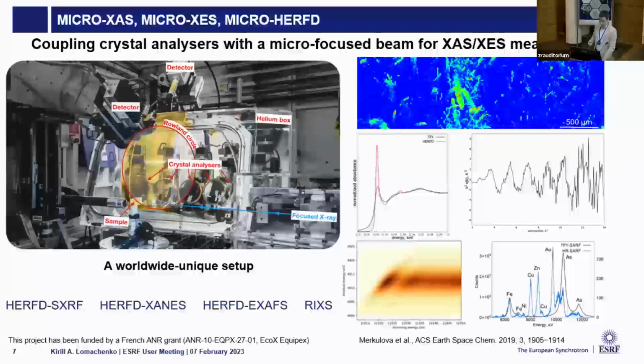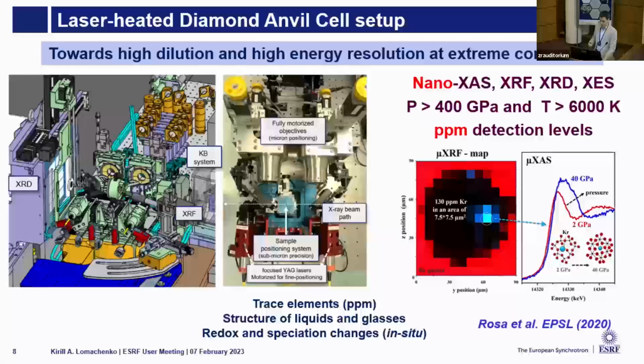The next flagship setup is designed by Angelica Rosa. It's a laser-heated diamond anvil cell setup, which allows us to reach a very high pressure and temperature inside a diamond anvil cell. And here ID24 DCM is a very good instrument for the job, because to reach high temperature and pressure, the sample has to be very small.